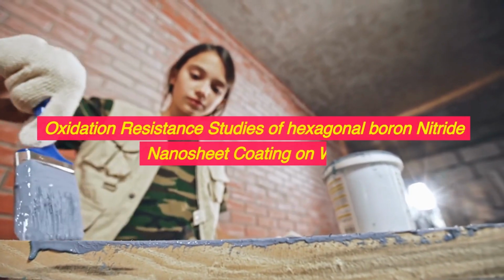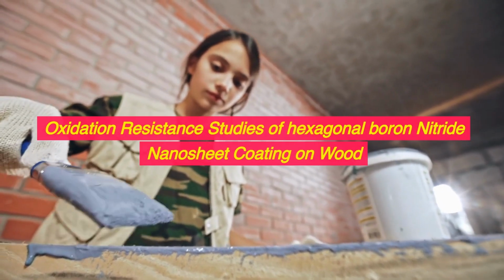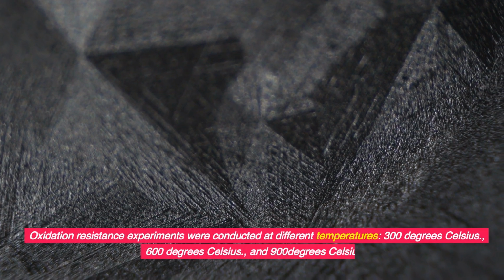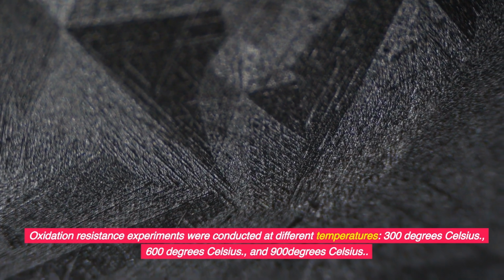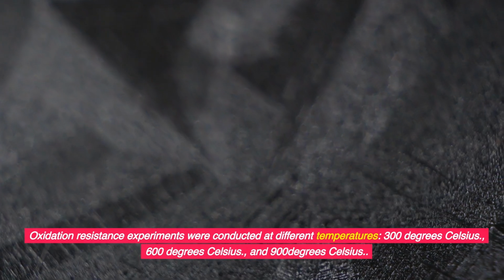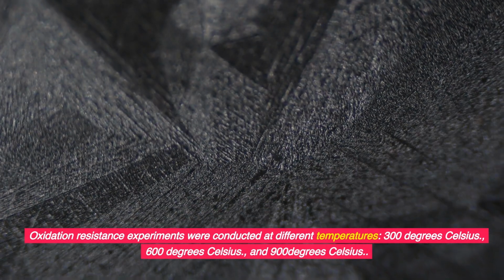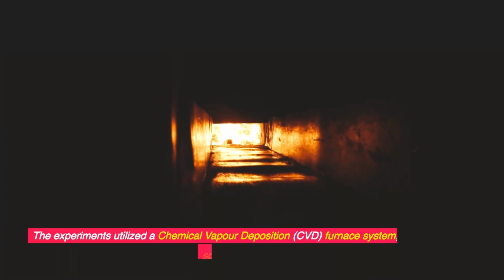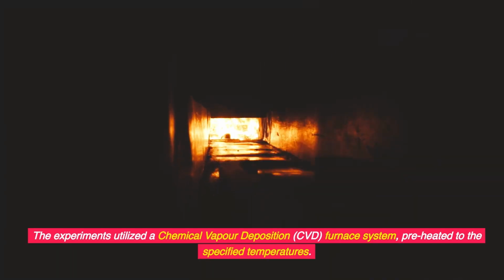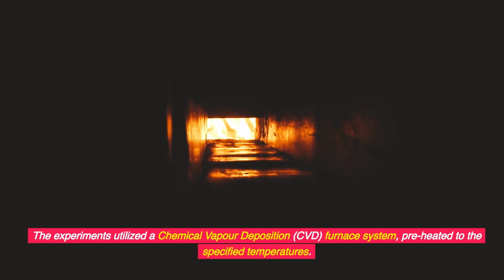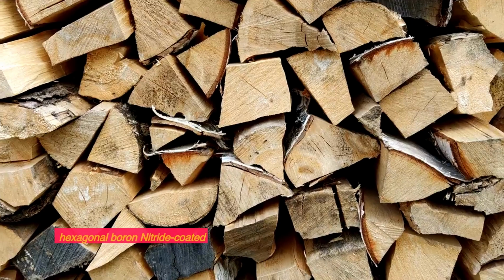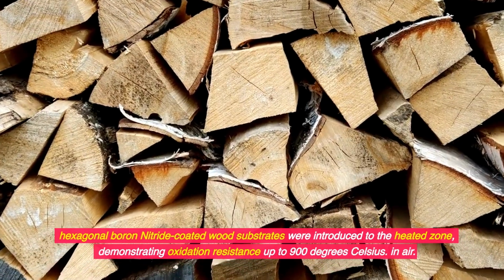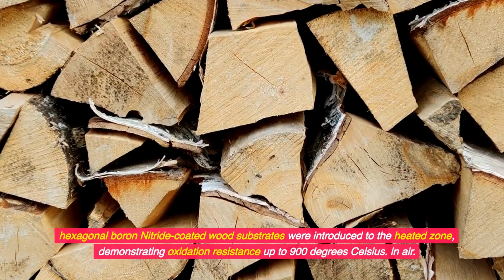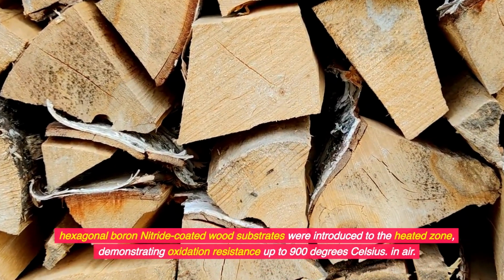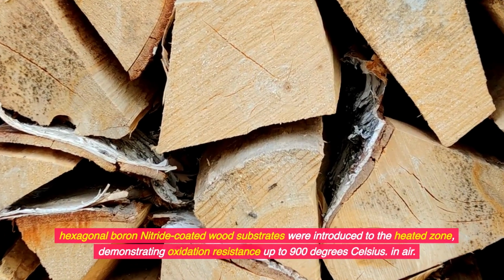Oxidation-resistant studies of hexagonal boron nitride nanosheet coating on wood. Oxidation resistance experiments were conducted at different temperatures: 300 degrees Celsius, 600 degrees Celsius, and 900 degrees Celsius. The experiments utilized a chemical vapor deposition (CVD) furnace system preheated to the specified temperatures. Hexagonal boron nitride-coated wood substrates were introduced to the heated zone, demonstrating oxidation resistance up to 900 degrees Celsius in air.